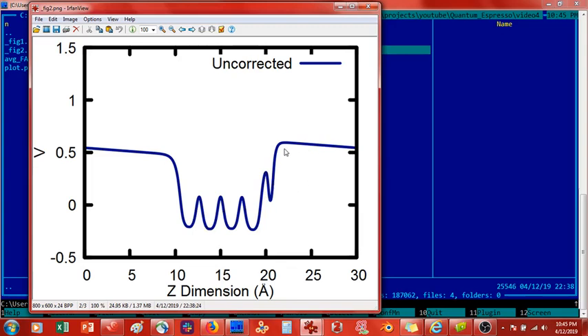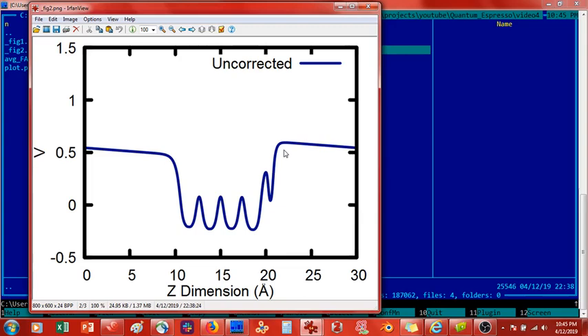And so for example, if this were actually flat here, then this dip here, which corresponds to the fluorine atom, might be a little deeper. And so if you're misrepresenting this potential, then whatever values you were going to report in your scientific publication might be misrepresented. And so what you want to do is you want to correct for this induced dipole. And you do that by actually applying a dipole of equal and opposite magnitude to cancel it out. And that's what we're going to do right now.